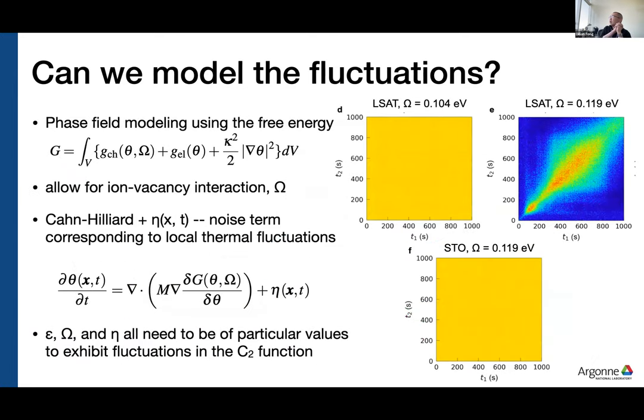So we had to go more complicated. So here I'll just demonstrate that. For LSAT with an interaction energy of 0.104 eV, we see no fluctuations in the two-time. We do see some fluctuations in the two-time when we switch to 0.119 eV, but it doesn't fluctuate back and forth, which is what we really wanted to see. And getting the flat two-time is relatively easy for the sample grown on strontium titanate.